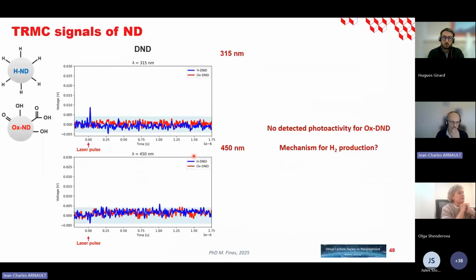I will start with the detonation nanodiamonds, either hydrogenated or oxidized, and you have the TRMC signal we were able to measure in the UV range or in the visible range. And the first point is that the oxidized detonation nanodiamonds don't exhibit any photoactivity in the TRMC signal. This is something that raises questions. You remember that for hydrogen production, these were the most powerful particles. But when you look at the photoactivity in these conditions, you cannot measure any signal.